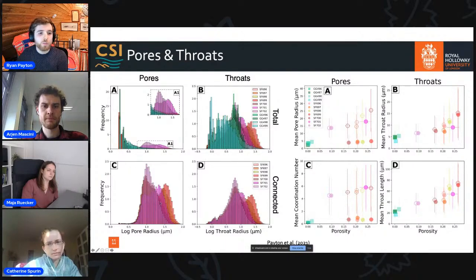In some cases, you may find that the smaller pores are crucial to connect the larger pores together. But this doesn't appear to be the case in what we found here. It's the same case for the throats as well. We can see that these smaller throats are lost when we look at the connected case. So again, the larger pores and larger throats are really crucial to the connectivity here.